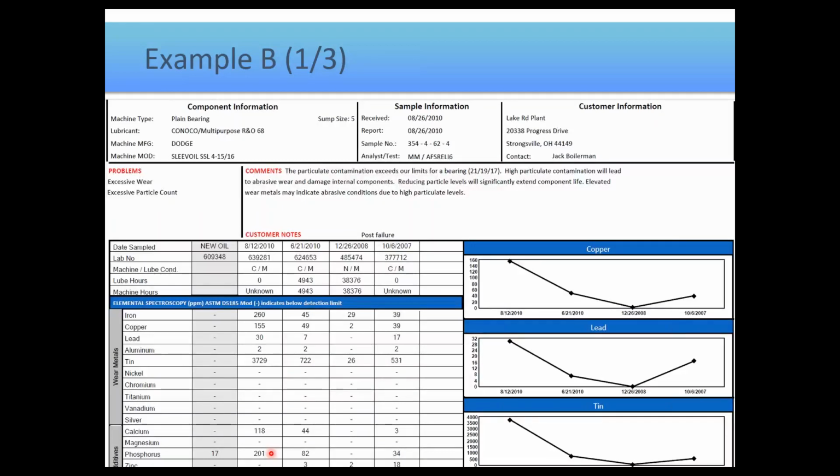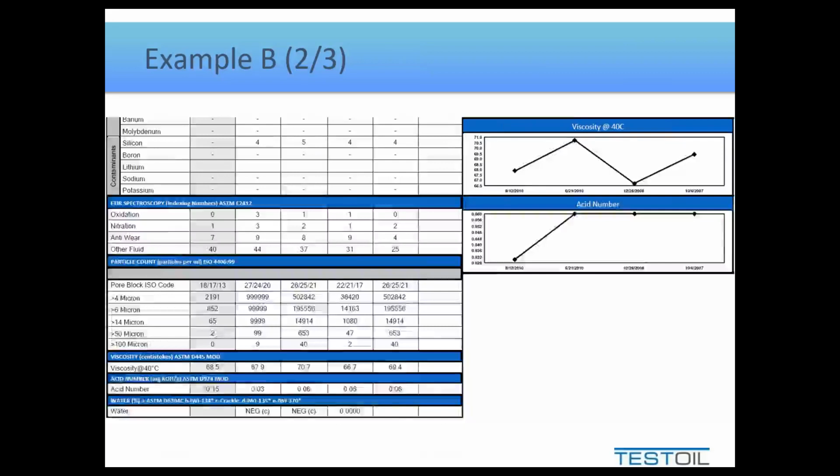So that's why I returned to the seal solution and say, yeah, well, if you over-grease the seal, you would have failed the seal. If the seal failed, well, then contaminant could get in. So that's why I lean to something like that. But that's the basic procedure that you follow in terms of reading these reports.